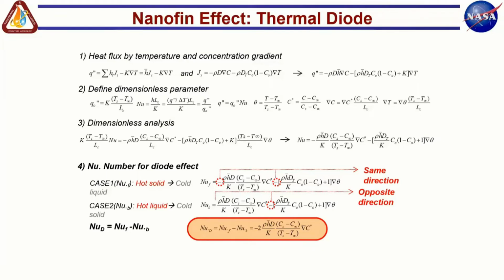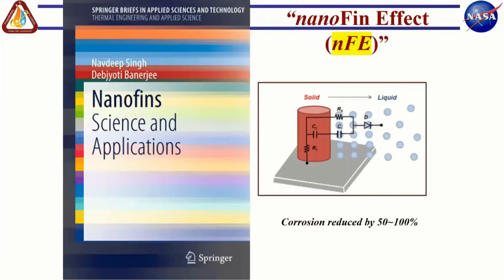So if you subtract the Nusselt number forward from the Nusselt number backward, you get a net term which is proportional to the concentration gradient. And so, in other words, for the same temperature drop, a hot nanoparticle actually pumps more heat than a cold nanoparticle getting pumped with heat from a hot fluid, essentially. So that was a revolution, based on this work.